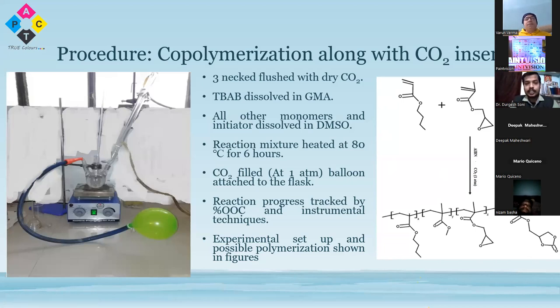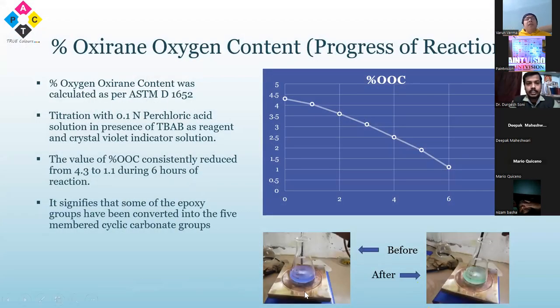In this way we can track the carbonation reaction, that is the conversion of epoxy into the cyclic carbonate group. So percent oxygen content, as discussed, is based on the titration method. Initially, it is titrated with the 0.1 N perchloric acid solution in the presence of tetrabutyl ammonium bromide as a reagent and crystal violet indicator solution. So during the course of reaction, during 6 hours of reaction, the percent OOC reduces from 4.3 to 1.1. It shows that the epoxy group content has reduced. And since we have connected the CO2 balloon, that means the epoxy groups are converted into the cyclic carbonate group. It was also verified by the FTIR spectra. I will show you.